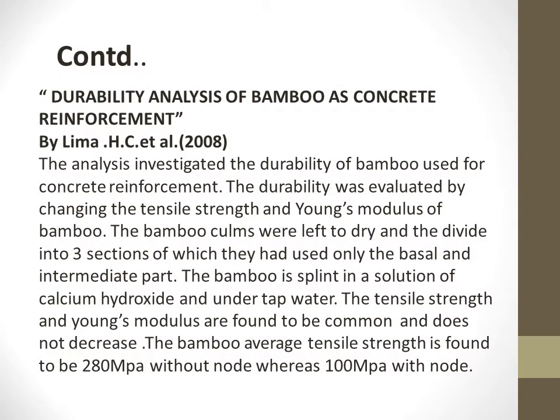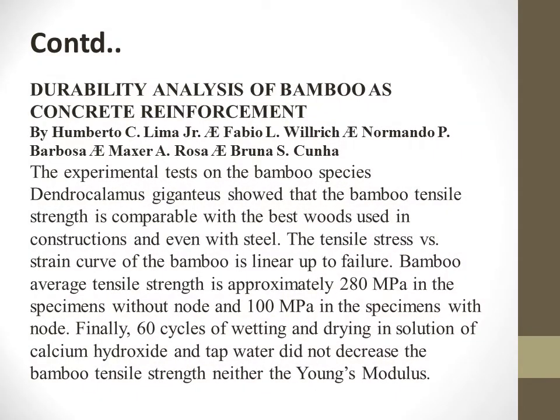This is another journal on the title Durability Analysis of Bamboo as Concrete Reinforcement by Lima in 2008. The analysis investigated the durability of bamboo used for concrete reinforcement. He found out that the average bamboo tensile strength was found to be 280 megapascals without node and 100 megapascals with node.